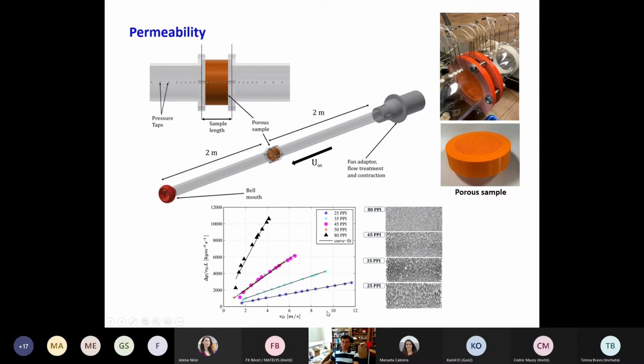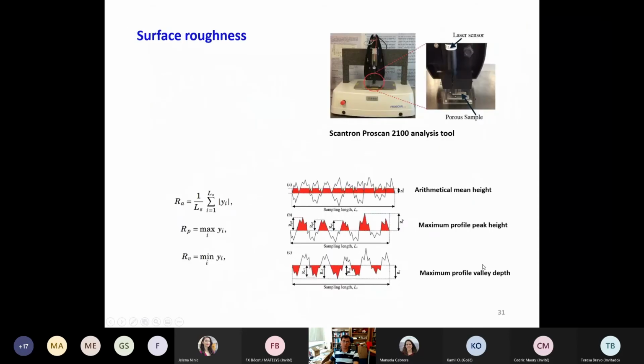This shows you some results of pressure drop versus velocity for different porous materials. You see the pictures here from 80 ppi. Ppi stands for pores per inch, all the way to 25 ppi, which is pretty coarse. And the gradient of these curves gives you the permeability of the porous material.